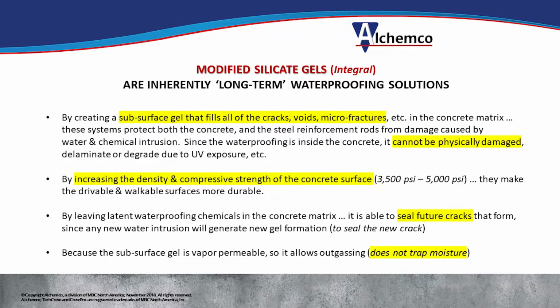And after that, one of the side effects of the waterproofing is that this material is going to increase the strength of the concrete. The test that we have done shows an increase of about 40%. So if you have a 3,500 PSI structure, on this 3/4 of an inch, this area is going to increase to 5,000 PSI. On top of that, it's also going to increase the hardness of the concrete. So not only the strength, but also the hardness.